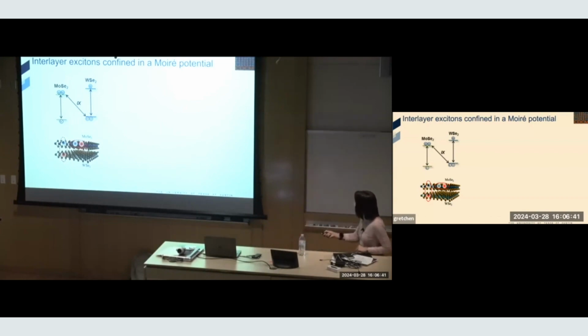So there are different ways to form electron hole pairs. They can be in the same layer or they can be in an opposite layer or two different layers. So this, I call them intra-layer exciton. This, interlayer exciton. Their properties are very different because the interlayer excitons, they're separated further apart. They have much longer lifetime.